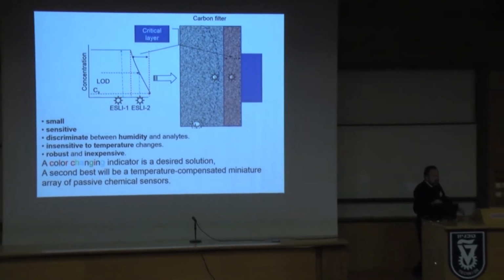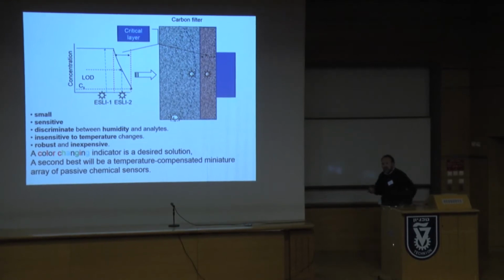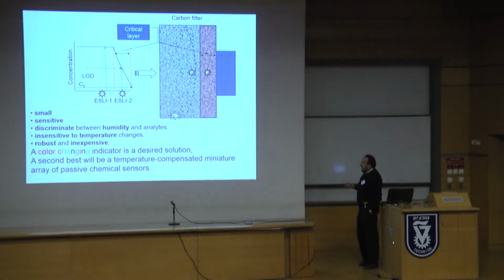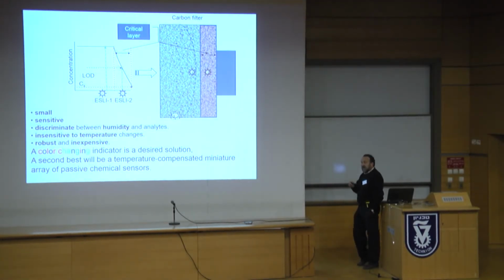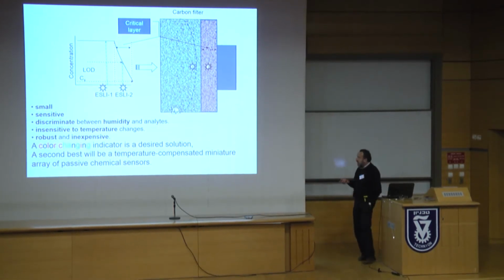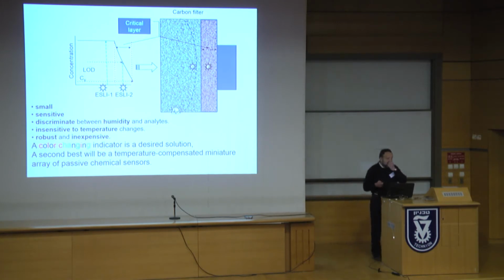In general, the indicator has to be small and sensitive enough, and has to discriminate between humidity and analytes, but also between groups of different analytes. It has to be insensitive to temperature changes. When a large concentration of material is absorbed in the carbon, the temperature rises, and you don't want the temperature rise signal to say anything about your cartridge. Of course, it has to be robust and inexpensive. A color changing indicator is a desired solution, but as I told you, only about two or three of them are available. The second best is a temperature compensated miniature array of chemical sensors. And that's what we tried to do.